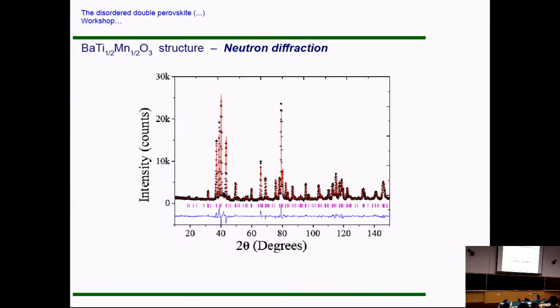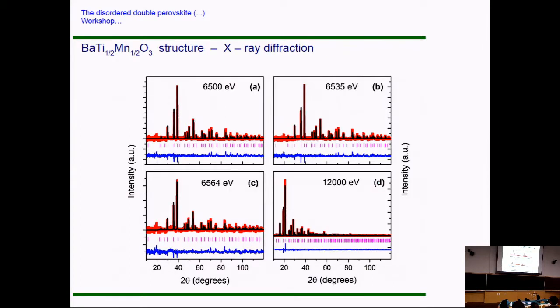The other thing supporting our structure is neutron diffraction measurements. It is the result of recent Rietveld refinement. We can discuss later. We have some other data. And this is as well what we did with X-ray diffraction. But one of the main problems is that from the point of view of both neutrons and X-rays, titanium and manganese look very much the same, right? It's very hard to distinguish the occupation because of the coherent scattering length.